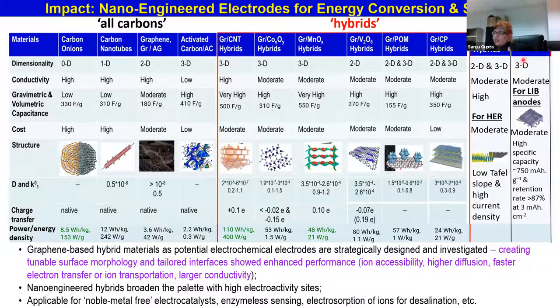So here we utilized the graphene again, with porous silicon. The other candidate for the anode was silicon, and although it has a higher capacity, it's also very rigid, so it can break faster. So structural breakdown or degradation is not as good as if you combine it with some softer systems. So we used a porous graphene, coated it with carbon, and then combined it with the porous silicon, and we tested some of these in the lithium ion battery. That's the kind of work we did here, and in the first experiments it did provide a reasonable specific capacity and so forth.